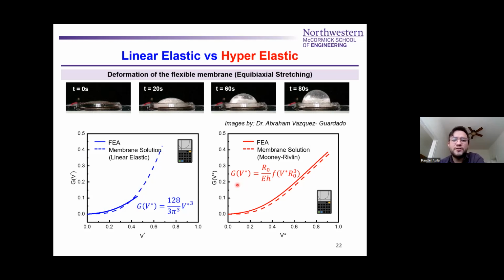But in reality, we'll have some hyperelasticity in our membrane, and we can solve it by using a generalized hyperelastic model, where we have the contributions from the membrane in our function. In this case, it's going to be like the Mooney-Rivlin model, where we can see that the finite elements, the continuous red curve, and the membrane solution agree very well. And it makes sense that the membrane solution is below the FEA, because you're neglecting the bending effects of your membrane when you're using the membrane solution. So it goes below the FEA.